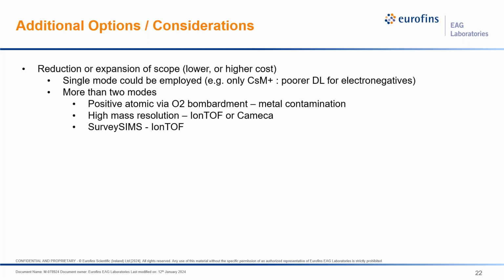Some additional options and considerations when doing this type of thin film characterization. We could either reduce, lowering cost, or expand the scope, at higher cost, depending on what you need. So for example, we could simplify the analysis to have only a single mode. However, in that case, we would not be optimized for all the elements. We'd have to have a compromise. One example is that we would have a poor detection limit for electronegative species if we only used the CsM+ mode. We could use more than just two modes.